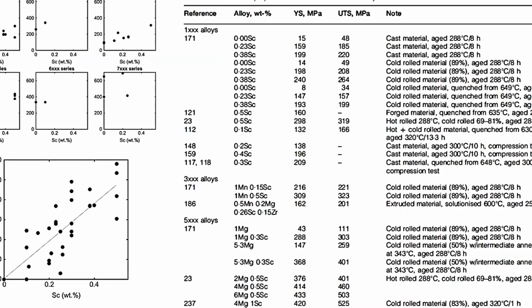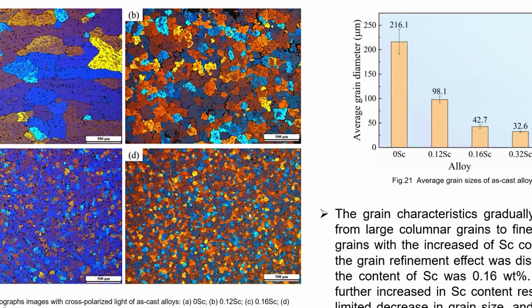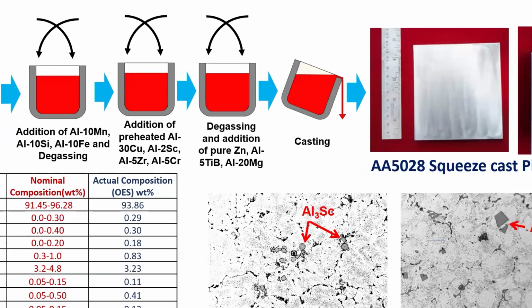So I will just show an example. For example, 4 magnesium with 1 scandium, you can see that UTS is 525 and the yield strength is almost 420. So you can see enhanced properties. The addition of scandium reduces the grain structure. If you don't have scandium, you can see very coarse structures. And addition of scandium at almost 0.3% reduces the grain size to a greater extent, thereby improving the properties. And the formation of Al3Sc precipitates also strengthens the alloy. So these are the Al3Sc precipitates which are getting formed.